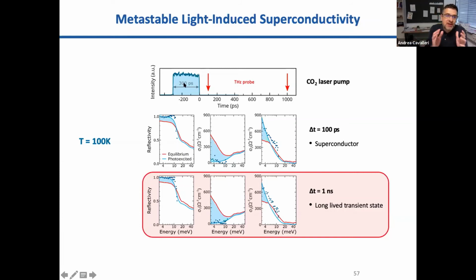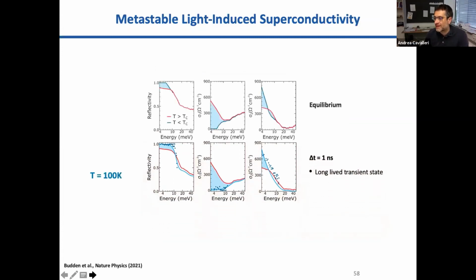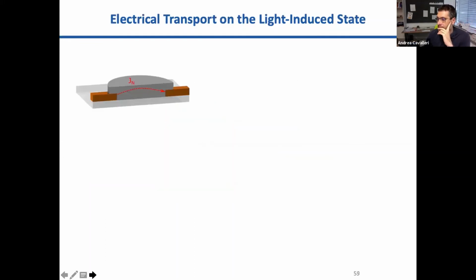So it appears that by driving the material with the same fluence longer, one acquires a state that is somewhat more rigid and actually lives, we found that it can live for about 12 nanoseconds. Okay, so this is a new discovery that is very puzzling. But it's one of the most exciting problems we're working on, and we really have no idea what is going on. And it looks like the initial intuition of driving a specific vibration to generate a long-lived, high-temperature superconducting state may not be the correct one.